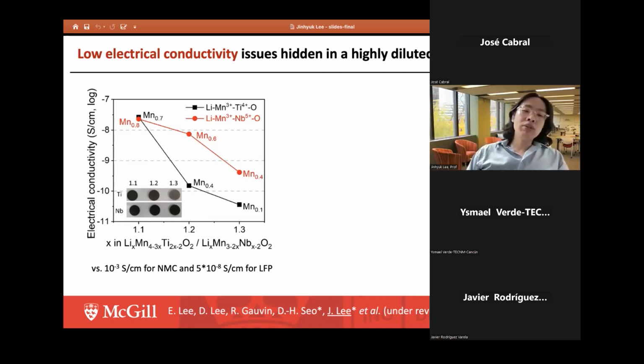And because of the low intrinsic conductivity, we found that if the active material content becomes larger and larger, meaning that the conductive carbon amount becomes much, much smaller, the performance becomes significantly poor.